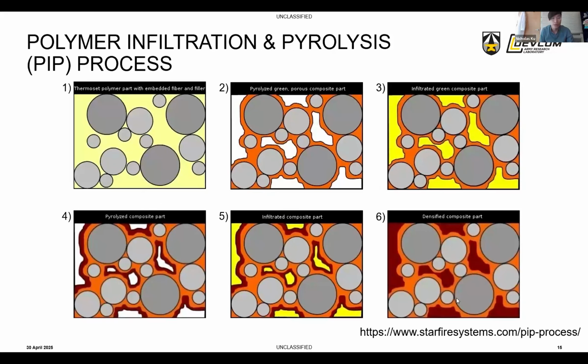So one of the areas of research that we're heavily investing in right now in binder jetting is what we call polymer infiltration and pyrolysis, a PIP process. Basically, you would create a powder preform through binder jet. We're infiltrating this with a pre-ceramic polymer, a silicon-based polymer that when we pyrolyze will form silicon carbide. So you infiltrate it with the resin, you pyrolyze that, it opens up pores and cracks, then you re-infiltrate all those pores and cracks with more resin, and so on and so forth. It's a cyclic process until you fully densify your part.